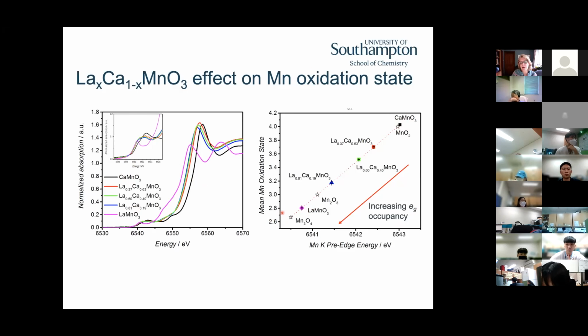And then we have the calibration curve made from some reference materials. And so you can see that we do indeed see the edge shift. There are also some interesting changes in the octahedral structure here that can come out from further analysis of the XANES, right? But we're seeing the average oxidation state of the manganese ions changing as we would expect as we change the composition.